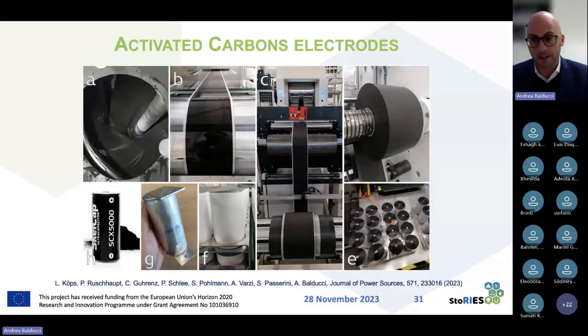So to have a positive electrode with a negative electrode, which are in this case identical. In a supercapacitor, the positive and negative electrodes are the same, not like in a lithium-ion battery where we have different materials for positive and negative electrodes. We have a separator in between. We have a multilayer, which will be rolled, like in this case. Then this roll is introduced in a can. The electrolyte is filled in, and then the system is closed. Once it is closed, it is prepared like any kind of cylindrical cell to be then sold. And this is the way the industry realizes carbon electrodes and implements them, in this case, in cylindrical cells.